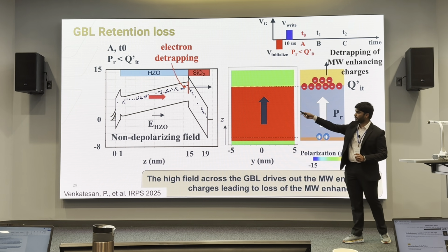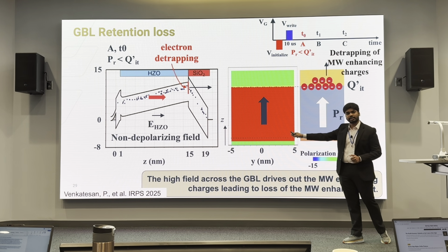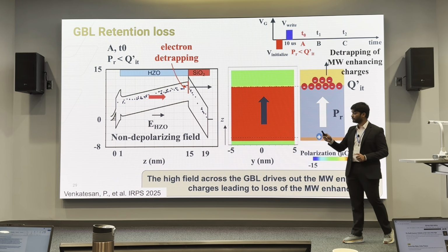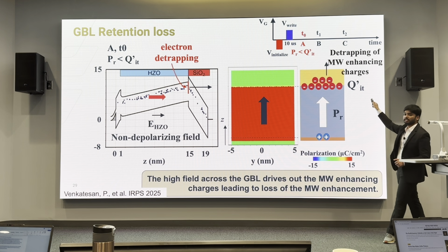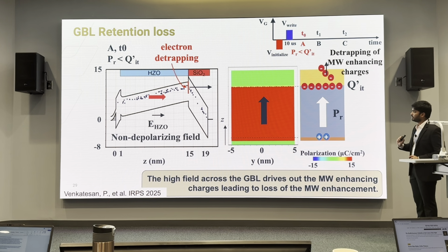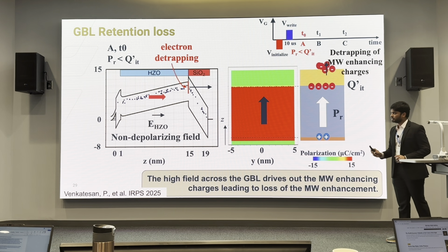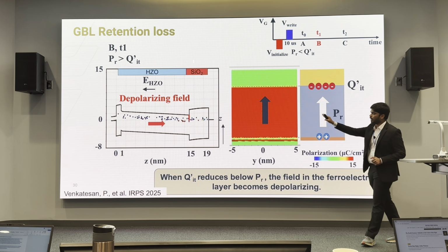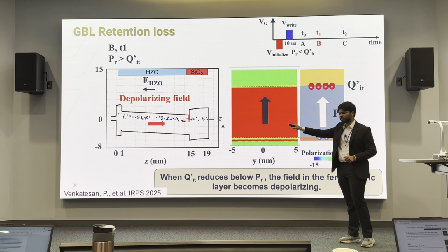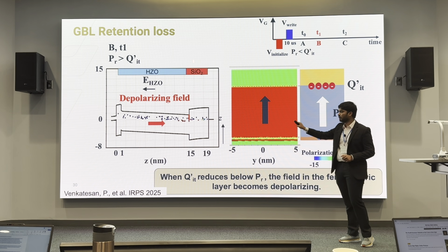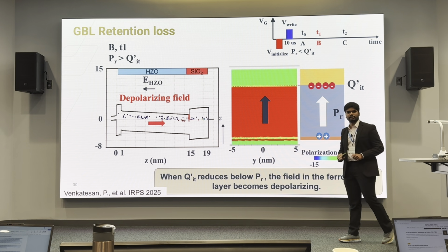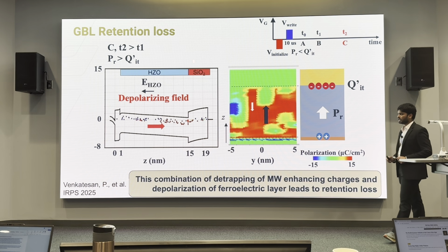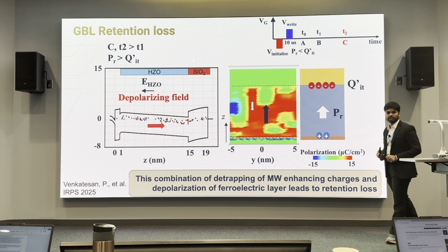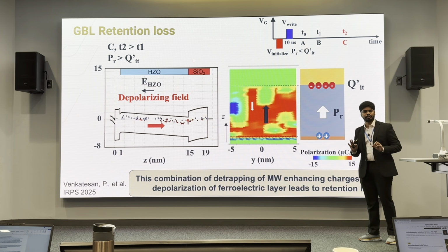But there is a huge field across the SiO2 layer, which causes detrapping of the charges at the ferroelectric dielectric interface. So now as these charges are detrapped, the field across the SiO2 layer decreases, which means there's going to be no more detrapping, but the field across the ferroelectric layer turns depolarizing. And over time, the ferroelectric layer depolarizes, leading to a 2-stage retention loss.